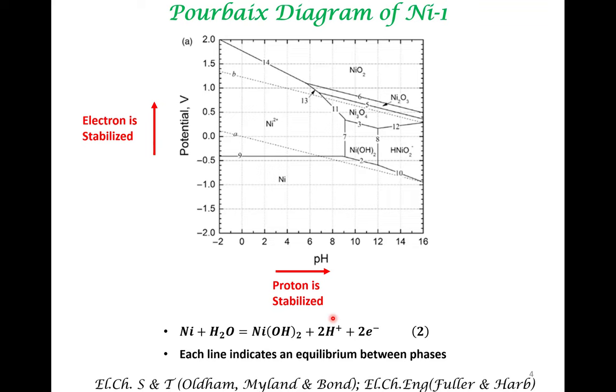You can ask two kinds of questions. You can keep a potential constant and ask: as you change the pH, what gets transformed into what? For example, if the electrode potential is kept constant at −0.5, as you go from an acidic pH to a basic pH, the proton is getting stabilized, so this side gets favored. Therefore, nickel gets transformed into nickel hydroxide as the pH goes from the acidic region to the basic region. That kind of information can be seen from the Pourbaix diagram.